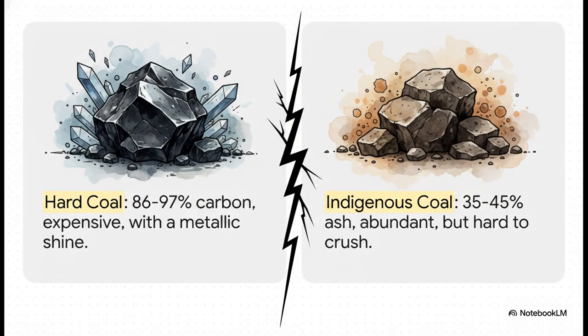But the real story here is in the data. That expensive, premium hard coal, it's packing an impressive 86 to 97% carbon content. On the flip side, our highly abundant Indian indigenous coal carries a massive 35 to 45% ash content. That high ash is a major industrial bottleneck because more ash means more slag and wasted heat in the furnace. But because of national priorities to reduce import dependency, we absolutely have to figure out how to use it efficiently.